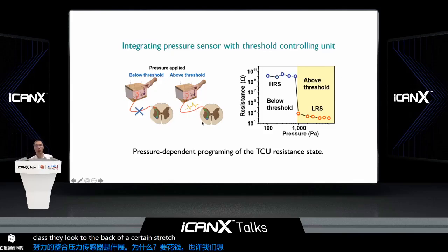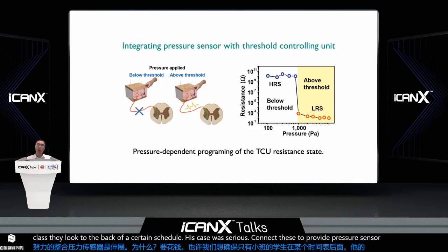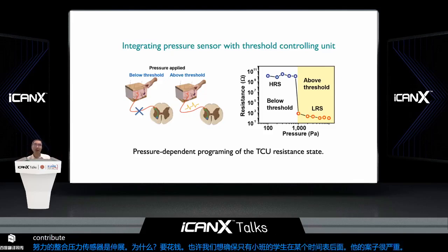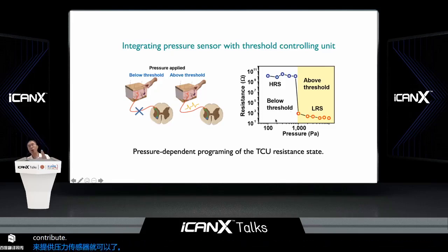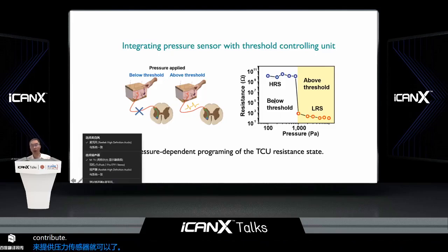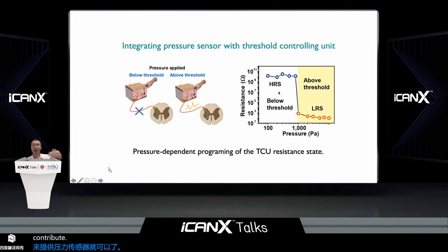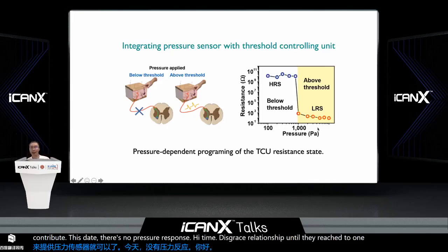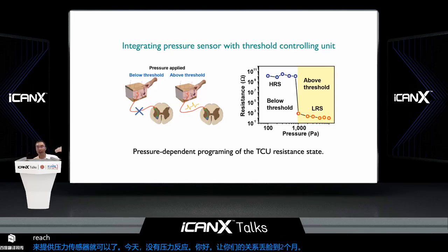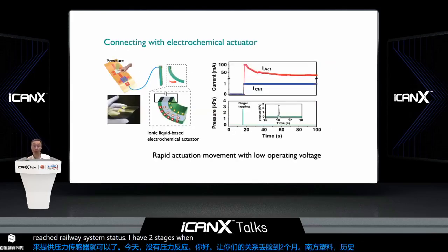In this case, we serially connect these two devices, the pressure sensor with our threshold controlling unit composed of ZIF-8 films. We find that at a low force below 1,000 Pascal, it is in the high resistance state. There's no pressure response, no high current. It's below threshold until they reach 1,000 Pascal, at which point they reach the low resistance state. Now we have two states, and you can really operate this kind of device.